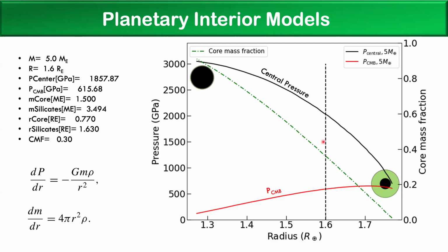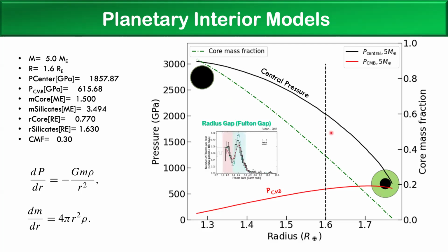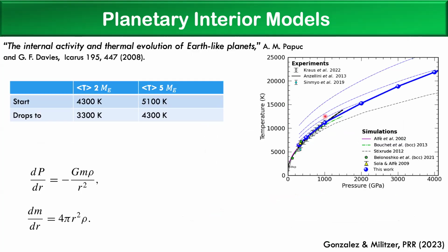So in this case, we want to focus on planets that are 1.6 Earth radii, which again has to do with this radius gap. We consider that planets of about that size are rocky, because larger planets are likely to contain substantial atmospheres. And we have these pressures that I will look at in the phase diagram of iron. So comparing with previous models that have been trying to address this question, you will see in the literature that very low temperatures have been proposed for the average temperature at the interior, on the order of 5,000 Kelvin.